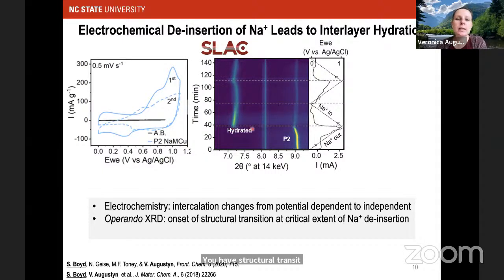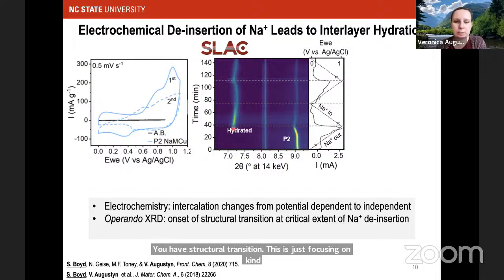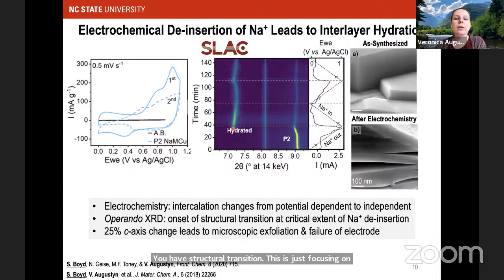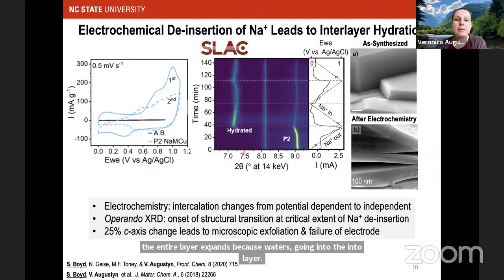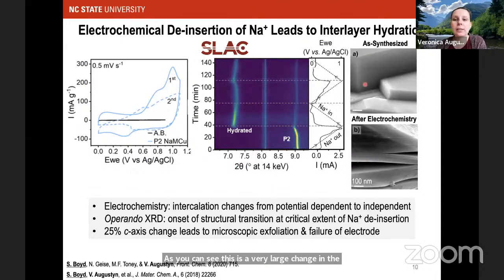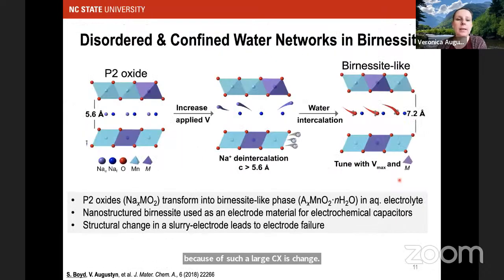This is just focusing on the major peak that changes, which is this interlayer peak, where you form a hydrated phase. So the interlayer expands because water's going into the interlayer. As you can see, this is a very large change in the interlayer spacing, and that actually leads to a microscopic exfoliation and failure of the electrode because of such a large C-axis change. And so it's kind of disappointing, but this is the mechanism that happens.